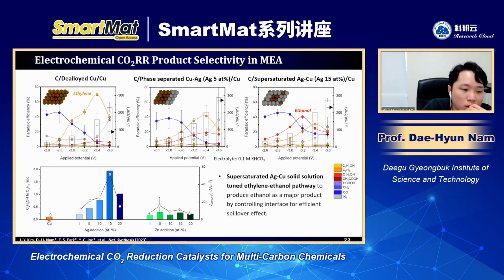So in the case of pure copper, the ethanol to ethylene ratio was very low. It means the major CO2R product is ethylene. But in the case of the 15% one, the supersaturated copper-silver interface, these are very effective to produce ethanol. And in the case of zinc, the ratio is very low, because zinc, although I didn't present it in today's presentation, is very miscible, and it is very difficult to control the interface between copper and zinc. So there is no big effect although we increase the content of zinc in this copper-zinc alloy. So this result represents the importance of the interface design for the copper alloy.